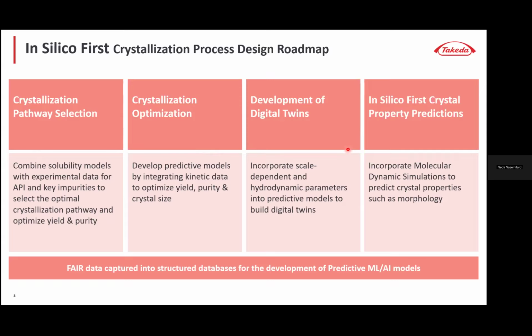The third bucket is development of digital twins, where we are really looking at scale-dependent and hydrodynamic effects. This is where these impacts start to matter much more. And the fourth one is crystal property prediction, and that can be the morphology, form, basically polymorphism of these crystals. The important point is that they are not 4 separate modeling exercises. They all sit on a common layer. It's a data backbone where we are really committing to FAIR data capture. So every experimental data point goes into the structured database to fuel our machine learning and AI models. Solubility, for instance: all the measurements with all the context would go there in order to build machine learning models for solubility. And then the data would be captured at each step.